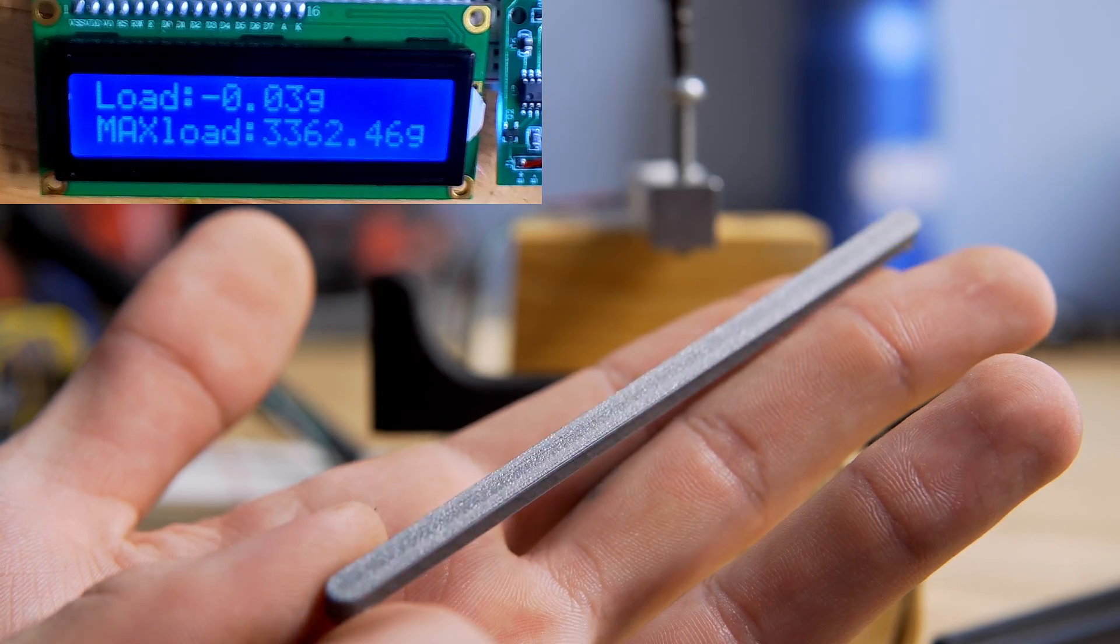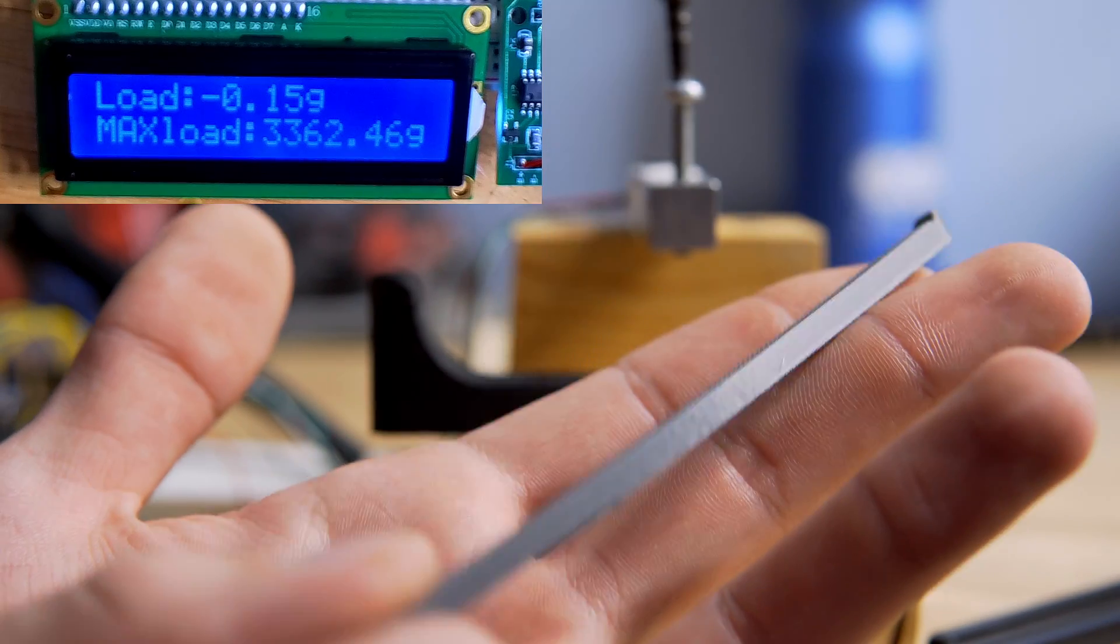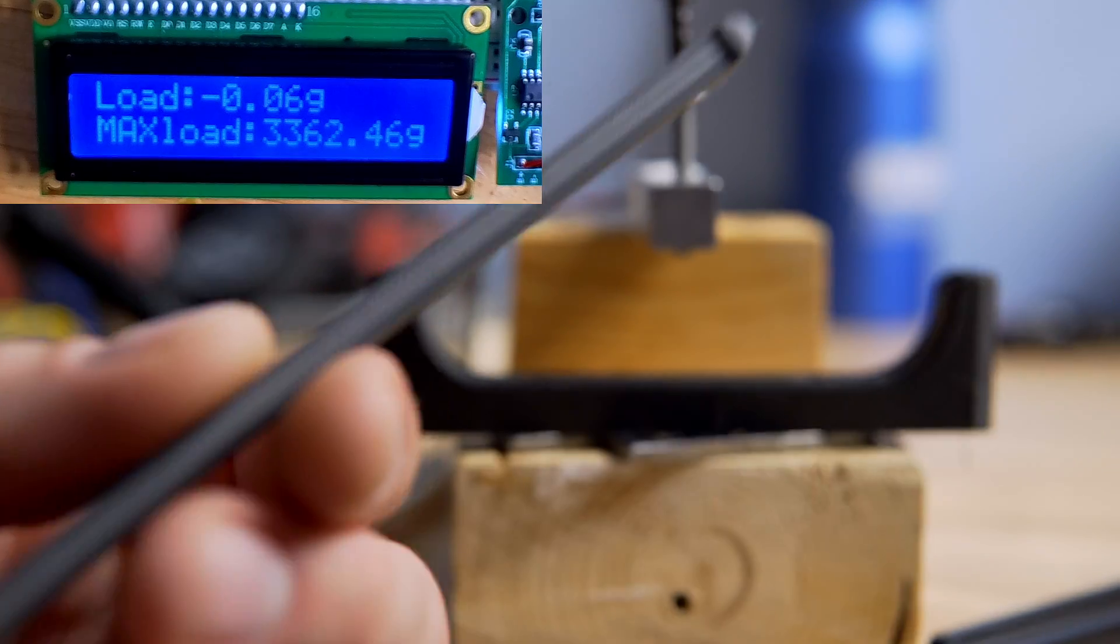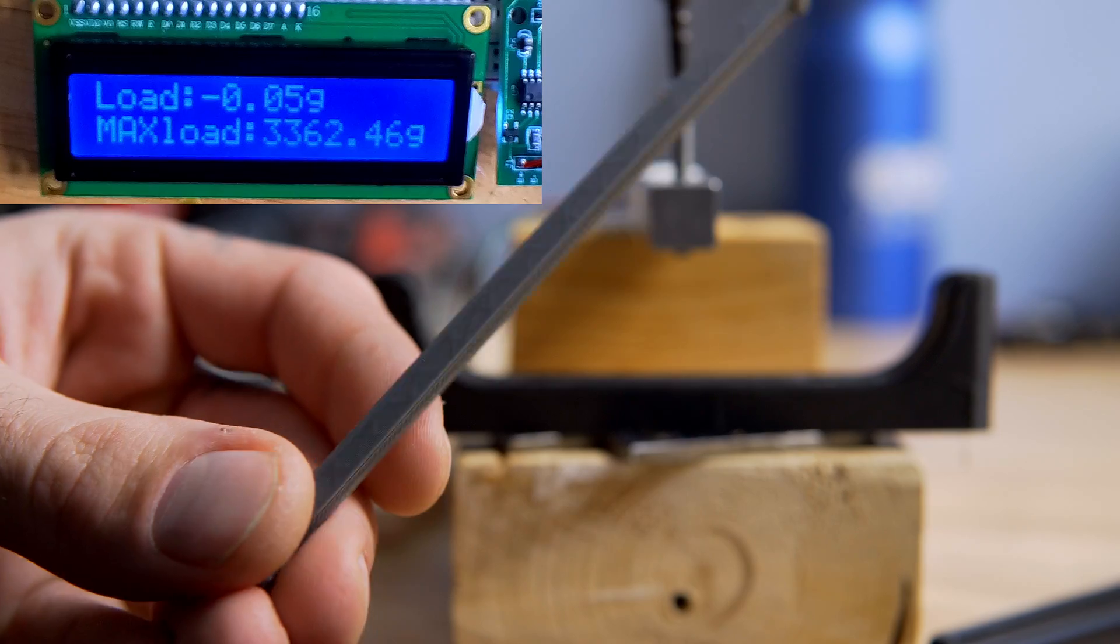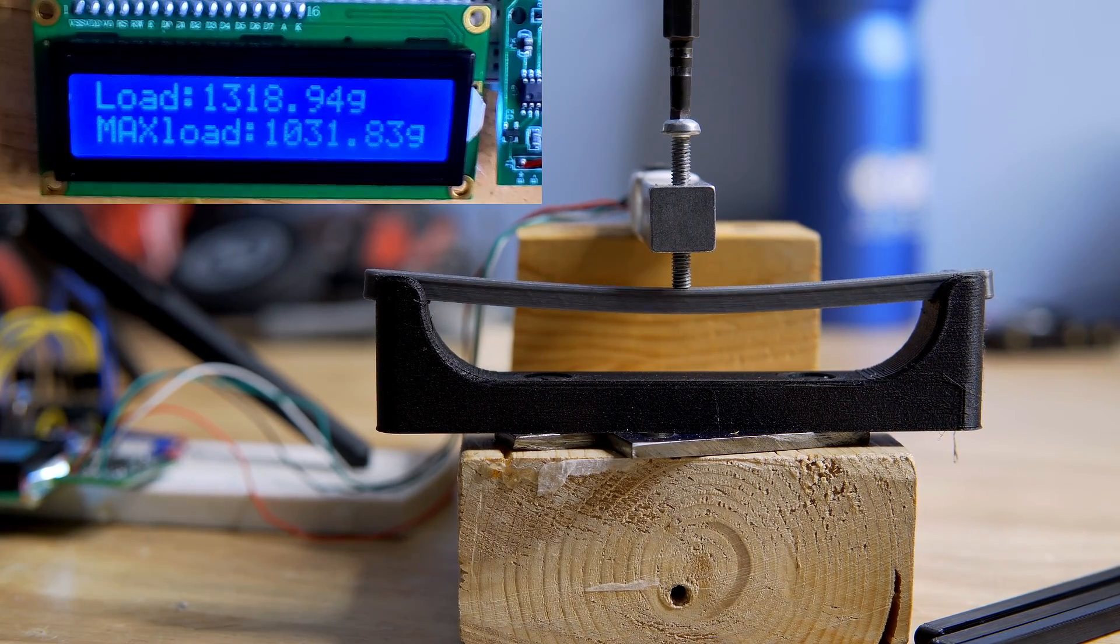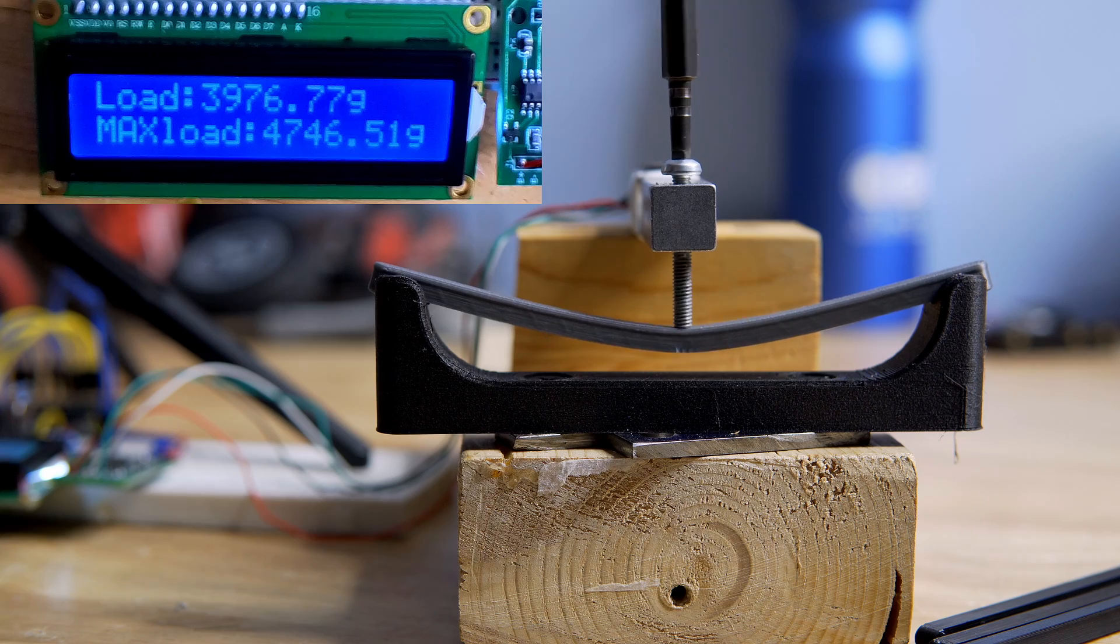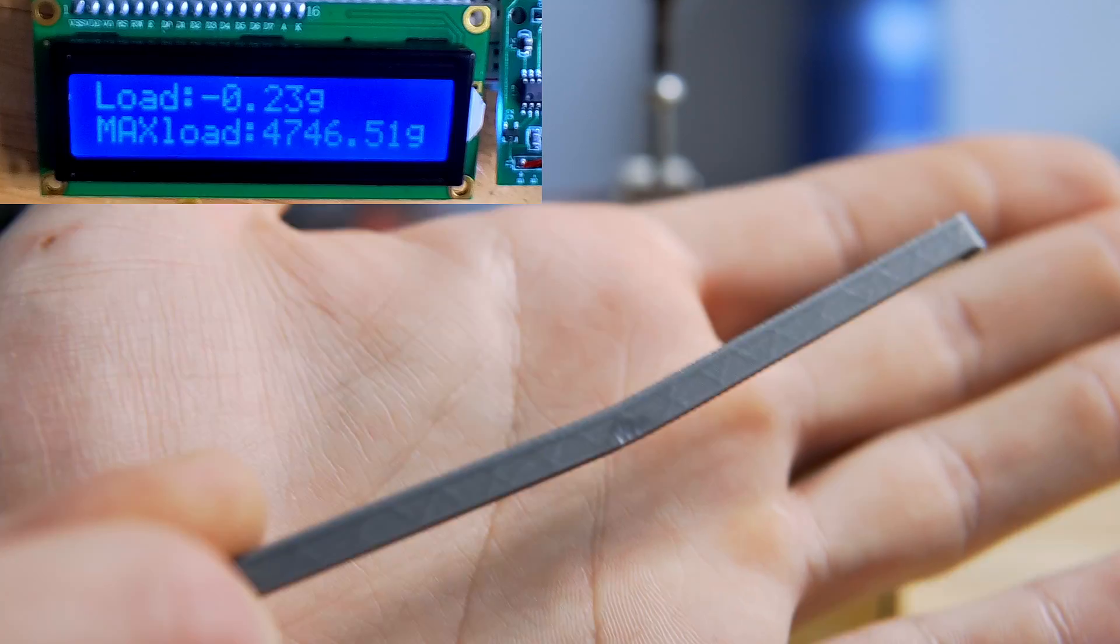Next up is regular PLA. Most people use PETG for its temperature resistance over PLA. I personally use PETG because it tends to be more flexible than PLA. PLA is stiffer and more brittle. And so let's see how this stacks up to the other two and then we can come to some final conclusions here. Our maximum load is 4746 here. Let's back it off and see if it'll return. So as you can see there's very slight cracking there. It did not return to its original position but it took way more load than the PETG did.